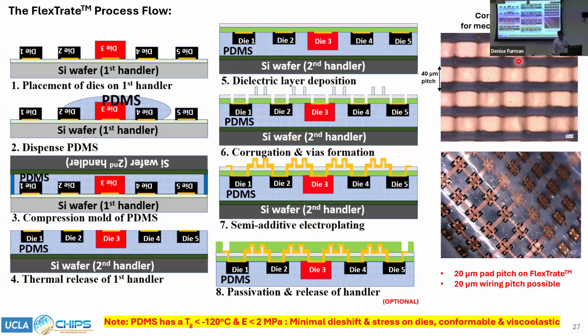And here you see a micrograph of the interconnects themselves. One of the things we innovated was that these interconnects are mechanically designed so that they don't crack on the PDMS, because the PDMS has a very different mechanical behavior compared to the much stiffer copper. A lot of work went into developing stress barrier layers between the PDMS and copper. And also, if you notice here, these wires are corrugated vertically. They go like a vertical serpentine, and that also helps to improve the mechanical reliability of the interconnects.